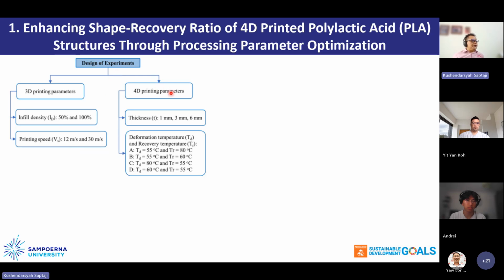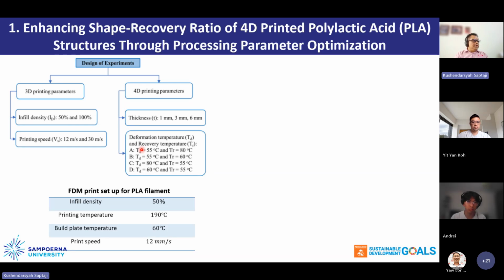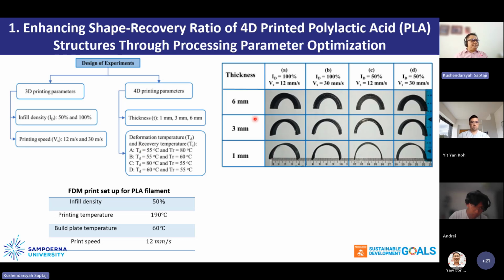The parameters related to 4D printing are the effect of the thickness, the deformation temperature and the recovery temperature. So after we apply the heat, we want to recover the sample back into the original or initial shape. And this is the specimen that we created. We created the U shape or semicircular shape like this for different thicknesses and for different printing parameters, which are the infill density and also the printing speed.